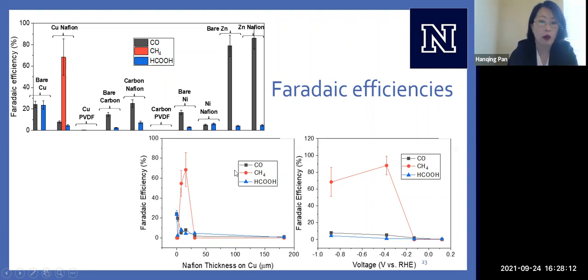Of course, we need to figure out what is our best optimal Nafion thickness. And so you can see that too thick will shut down our reaction. So anything thicker than 40 microns is too much. All of our experiments are voltage dependent. And so depending on the voltage, that changes up our products. And so the thing I want to point out here is this data point right here at minus 0.4 volts versus RHE, we're making 88% methane. So that's high, super high selectivity.